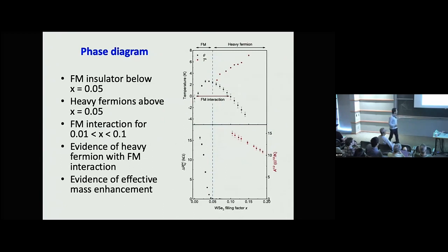So with that, here we try to summarize what we know in terms of this phase diagram, which is the doping density in the itinerant layer. You can see the anomalous Hall, the spontaneous Hall response, coming out below about 5% here. And that's going into an Anderson insulator. So it's a ferromagnetic Anderson insulator. And the Curie-Weiss temperature is positive over this range, from about 0 doping to about 10% doping. And the red dot here is the estimated Kondo temperature, or the coherence temperature scale. It's just continuously dropping towards this point.